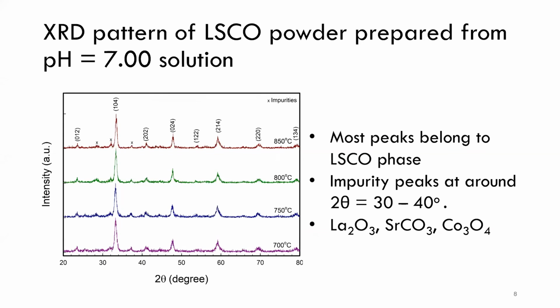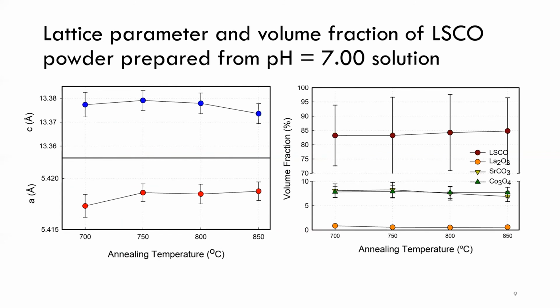Another set of samples was also prepared to determine if we can reduce the impurity phases that are present in the previous samples by increasing the pH to neutral. This time, the pH of the precursor solution was adjusted to 7.0. The XRD data shows most peaks also belong to the LSCO phase with the impurity peaks around 30 to 40 degrees. Similar suspected phases were also considered during the Rietveld refinement method. Lattice parameters and volume fraction were also calculated from the powder XRD data. It can be seen that there is no significant change in the unit cell size for all annealing temperatures. The calculated volume fraction also shows that most samples prepared were LSCO phase dominant.